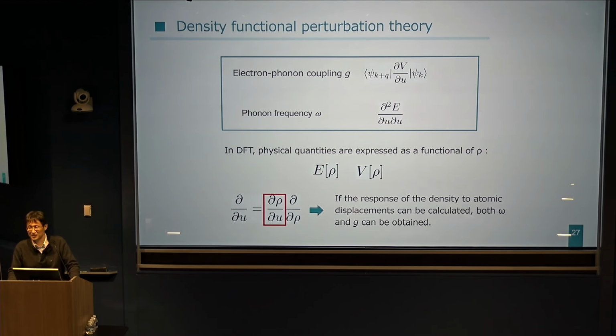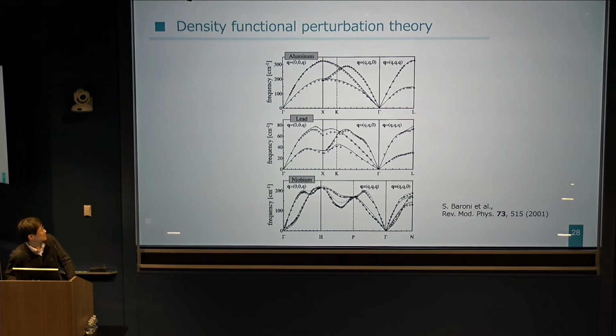But in density functional theory, all physical quantities are functionals of the density of the ground state. So if we know the response of the density of the ground state against the atomic displacement, then using this chain rule, we can calculate this derivative. And this strategy works quite successfully. This is the result of calculation for aluminum, lead and niobium. The solid line is the theoretical result, and the small circles or squares are the results of experiment. We see that the agreement between theory and experiments is very good.